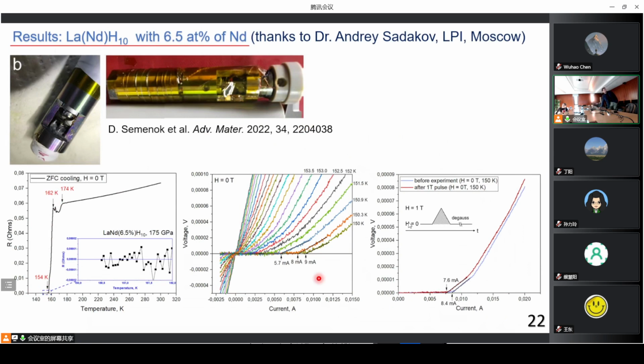You can see it here on the next plot. The critical current in the sample at about 150 kelvins is 9 milliamperes, where we can see the voltage appear. After applying such a current, 9 milliamperes, the voltage appears and the sample starts to behave as a normal metal according to Ohm's law.